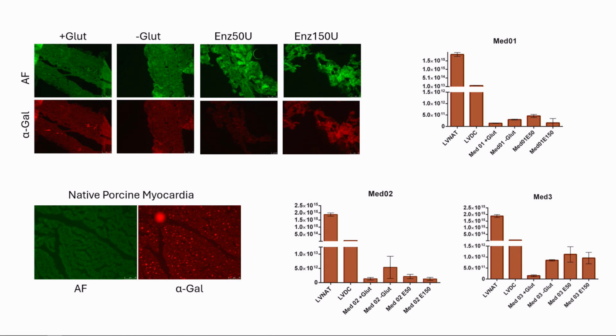With this, we saw the distribution of alpha-gal on the porcine surface. While we don't have a lot of signal, we treated them with an enzyme from green coffee beans, a very cheap source of alpha-galactosidase, and we found a bit of removal of the signals.